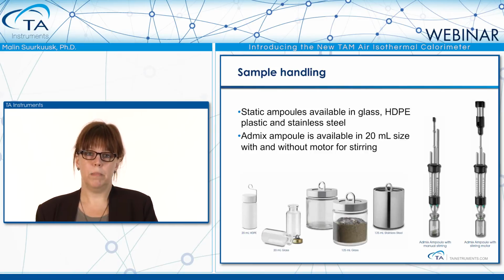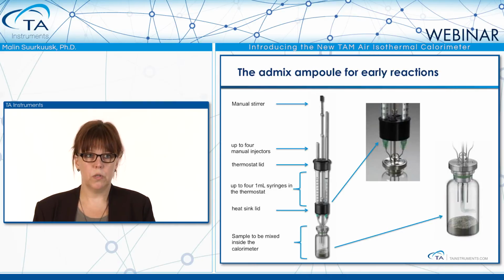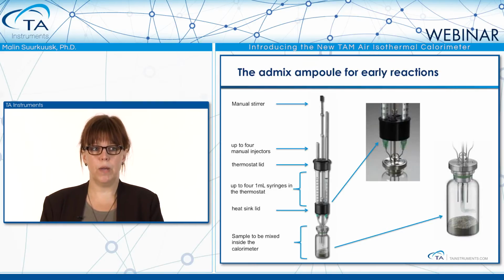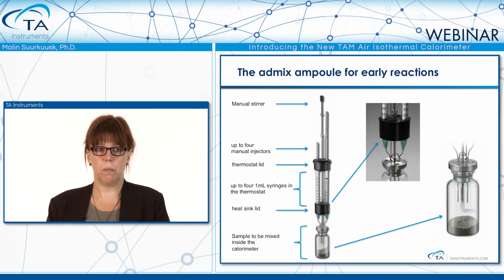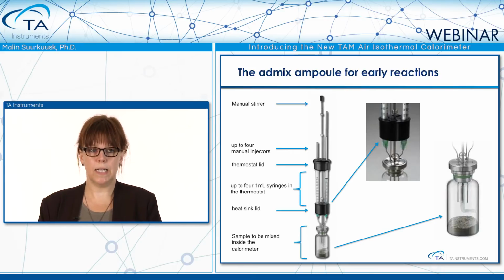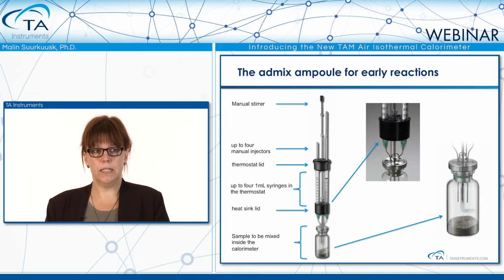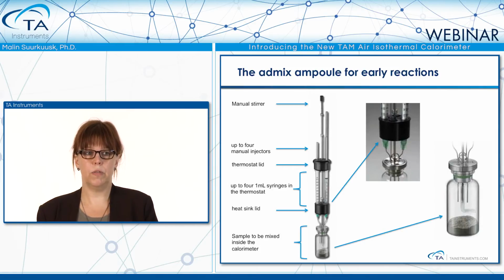For the 20 milliliter calorimeter, the 8-channel standard volume calorimeter, we also have what we call the admix ampule, as I mentioned, and that's possible then to add and mix samples inside the calorimeter. It can come with manual stirring or with a motor stirrer to be able to stir the sample inside. If we have a closer look at the admix ampule, which is used for early reactions, in the bottom you put your sample to be mixed, and this part with the glass ampule in the bottom, that's what sits inside the calorimeter. Above we have a heat sink lid, and that's the lid that sits in the secondary heat sink of the calorimeter.